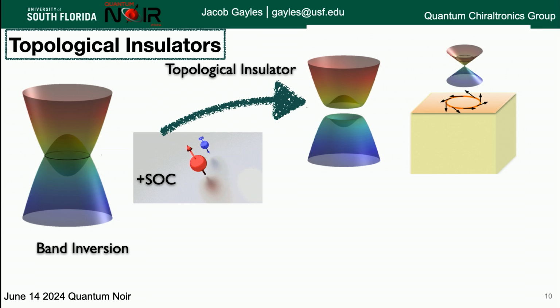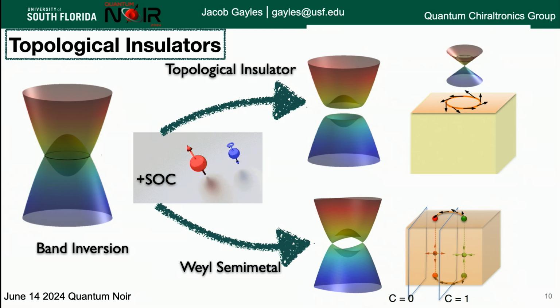Now, from there, what we can say is let's squeeze this material down to the smallest 2D layer. And this is just a metaphor, but we squeeze it down and then stack a bunch of them up, we can form a line of these Dirac points. And that's what's called a Weyl semi-metal. So you have a line of these Dirac points, and what happens is it cuts your Dirac cone on your surface in half, and what you get are these two what's called Weyl points that exist in your material. What's nice about these is they still have this linear dispersion, so they have very high mobility. You can use them for a lot of different types of electronics, and they still have also these very nice surface properties. And they're topological when you calculate this, and we'll get to that more later.